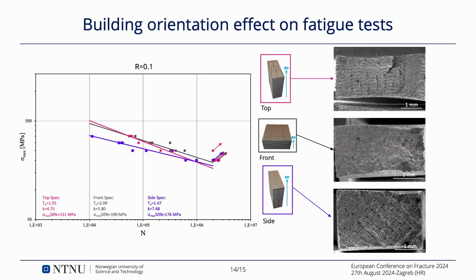So basically, for the top specimens, again, we can see the pores alignment, and it is difficult to identify a killer defect. It's most likely that there were multiple crack initiation points, while the front specimens are significantly more dense, and usually we could find the killer defect that was either on the surface or a worst surface plus subsurface defect. And finally, we have the side specimens, in which again you see the rasters, the inclination of the rasters. And here, again, it's difficult to specifically realize if the crack started from the surface or from an internal pore.